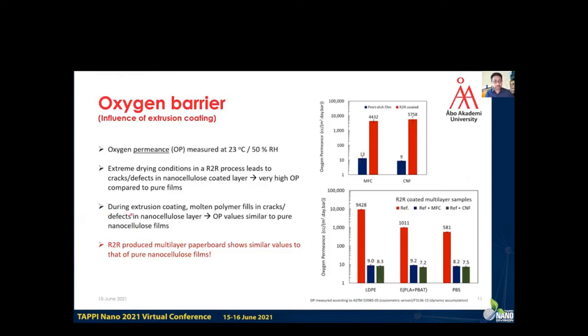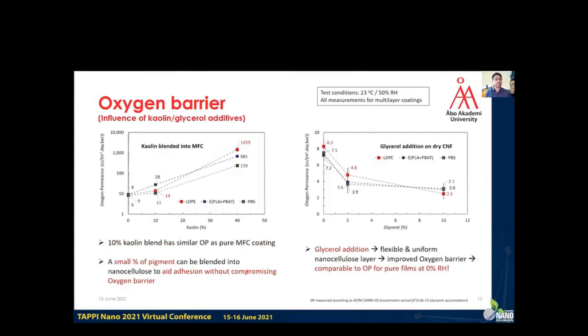So what is happening is during extrusion coating, molten polymer fills in cracks or defects in the nanocellulose layer, and therefore oxygen permeance values get better, and they show similar values to that of pure nanocellulose films, which is very promising. Now we look at the influence of additives on oxygen barrier, and the test conditions are the same: 23 degrees Celsius and 50% humidity, and all measurements are for multi-layer coatings.